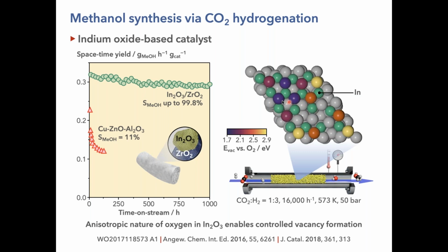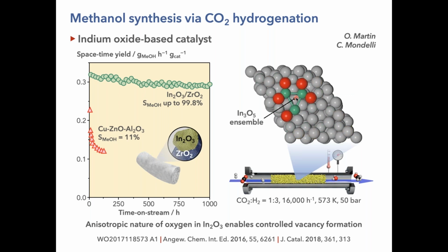And for example, these oxygens in purple have a much lower energy for being removed, that is, to create a vacancy, with respect to the yellow, for example, oxygens in the lattice, which are extremely hard to remove, which actually leads to a very difficult to reduce oxide under CO2 hydrogenation conditions. Because we can change those conditions of CO2 hydrogenation, we could produce a solid with a controlled vacancy chemistry, so that we are operating at a condition where only selected oxygen atoms from the surface of the catalyst are actually removed. The rest remain, and this forms again ensembles. In this case, it's an In3O5 ensemble with a vacancy where CO2 can activate and hydrogen can activate.